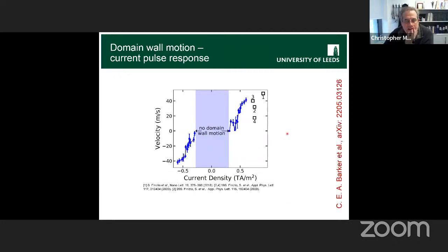Turns out these domain walls move reasonably fast. Here's velocity against current density. There's a region here in the middle where you get nothing, but it doesn't take a huge amount of current density to get up to 30-40 meters per second. This curve probably continues quite a bit further, but we didn't have many devices at the time we did this measurement, so we stopped here because we didn't want to explode anything. These are data points from conventional multilayer domain wall motion. What you can see is you can get motion at the same speeds for substantially reduced current density if you go to the synthetic antiferromagnet structure.